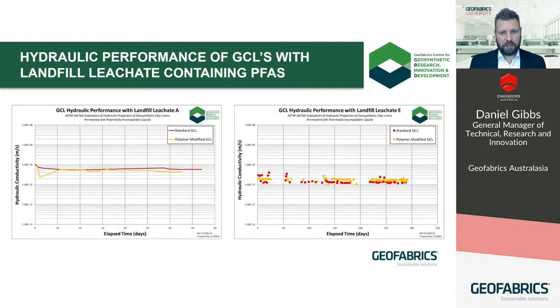Okay, let's take a look at the hydraulic performance. Here we can see the hydraulic conductivity of a standard GCL versus a polymer-modified GCL, both permeated with two different landfill leachates containing what I'd call reasonably typical or representative levels of PFAS as far as landfill leachates go. Leachate A gave final hydraulic conductivity values between 4.5 to 6 by 10 to the negative 11 meters per second for both GCL types, which is pretty good. And after around 9.5 months of permeation, leachate E returned values for both GCLs between 1 and 2 by 10 to the negative 11 meters per second, which is excellent.